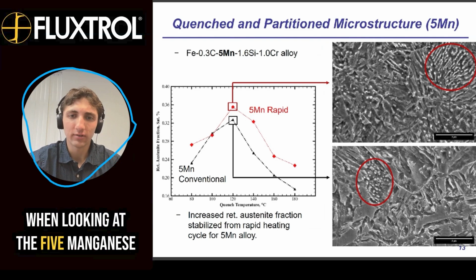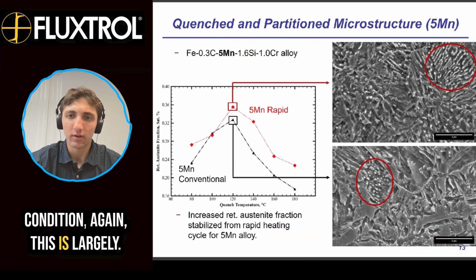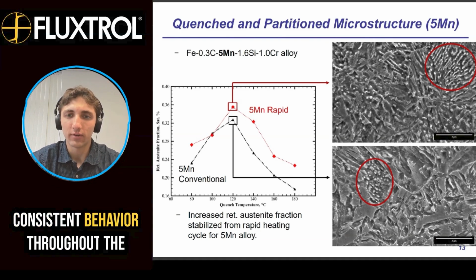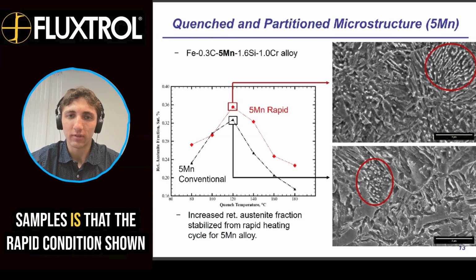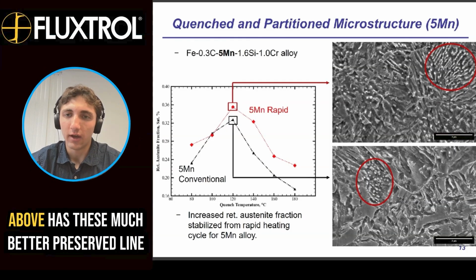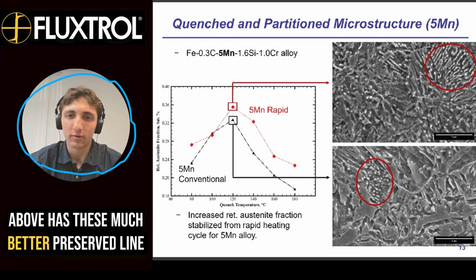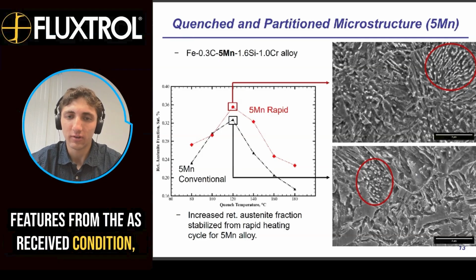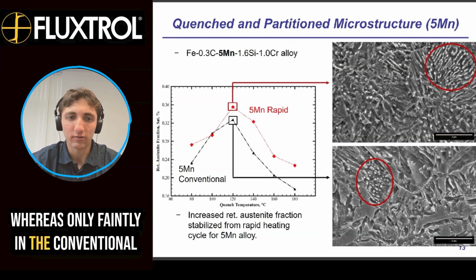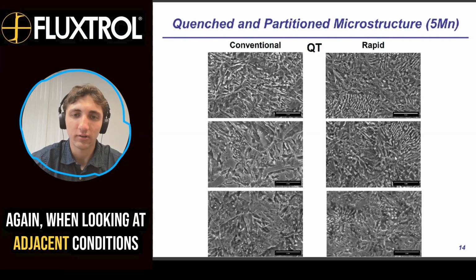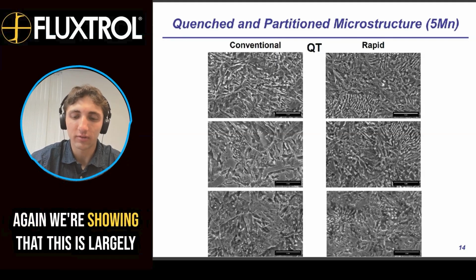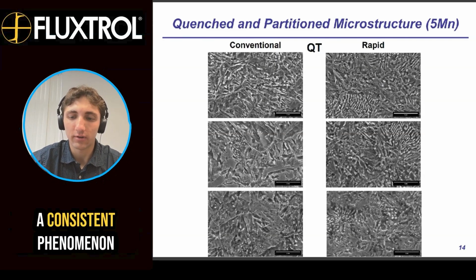When looking at the 5 manganese condition, again, this is largely consistent behavior throughout these samples, as the rapid condition shown above has these much better preserved line features from the as received condition, whereas only faintly in the conventional shown below. And again, when looking at the adjacent conditions, we're showing that this is largely a consistent phenomenon throughout the specimens tested.